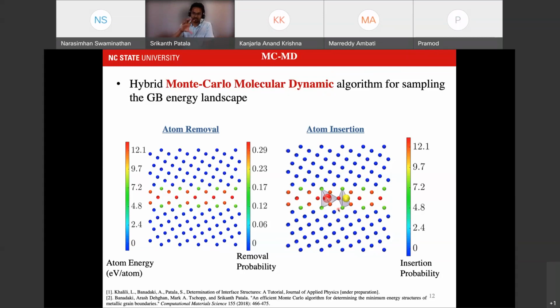But to capture the space charge region, you need a much larger system. And you can use a technique like this using swapping, inserting and removal, but you have to be very careful to make sure that your chemical potentials, going back to this idea of a grand canonical ensemble, are constant during your simulations. So again, it can be done in a Monte Carlo setting. We haven't done that yet, and maybe that's a good research topic to pursue as well.